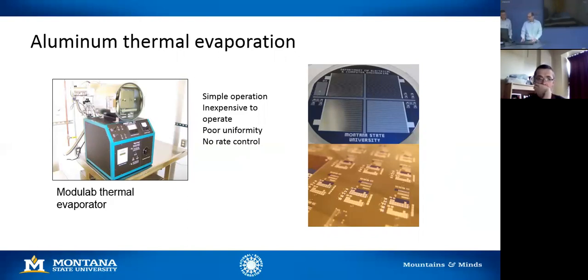For one example, we have a thermal evaporation tool. It's just for aluminum. We use this mostly for coursework, but some researchers use it also for electrical contacts. Simple to operate, inexpensive to operate, suffers from poor uniformity, and you don't have any rate control, which is a detail, but for electrical contacts, it's not really that important. So it allows us to have classes come in and do a lot of deposition work. A couple of wafers, a photovoltaic wafer that the class had done, and here's one with some transistors on it. Just the type of tool they would use to get these metallized layers on their wafers.